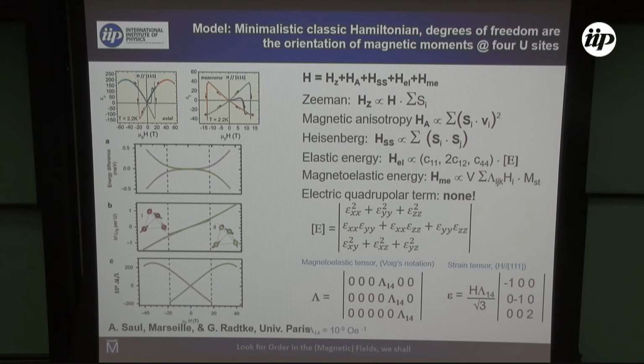We cannot reproduce, however, the transition between one and the other. We don't know yet what triggers this flip of domains at 18 Teslas. There's a speculation that maybe as the sample is distorted, the electric quadrupole component contribution becomes bigger and eventually dominates the antiferromagnetic dipole component in the order parameter, and maybe at that point the electric quadrupolar term needs to be included. However, we haven't done it yet. This is something for the future.